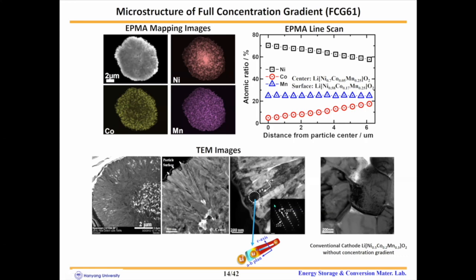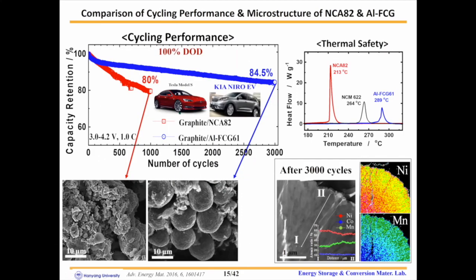Their length is estimated to be around 2.5 micrometers. Another unique feature of the FCG material is that all of the observed primary particles have their C axis aligned normal to the AB plane, providing the best channel for lithium diffusion. This is the comparison of the cycling performance of the commercialized NCA82 together with the aluminum FCG cathode materials. The long-term cycling performance clearly demonstrates the superior lithium intercalation stability of the aluminum FCG cathode.